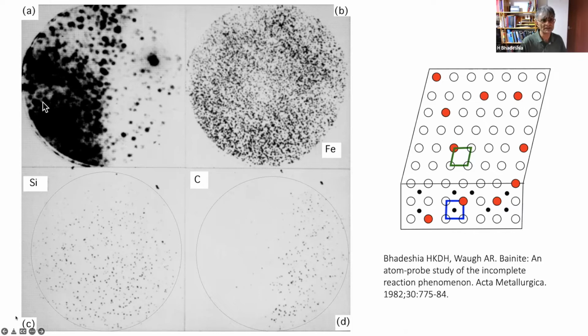Austenite is on this side and the ferrite on that side, and each dot represents a single atom. And by passing the atoms that you pull out through a time-of-flight mass spectroscope, you can identify what those atoms are and form an image just with those atoms. So here you can see the silicon is uniformly distributed across the interface, but notice the carbon is on one side, okay, in the austenite. So you might think something is not right. We've got a growth rate which doesn't allow carbon diffusion to happen, and yet we can see carbon has partitioned